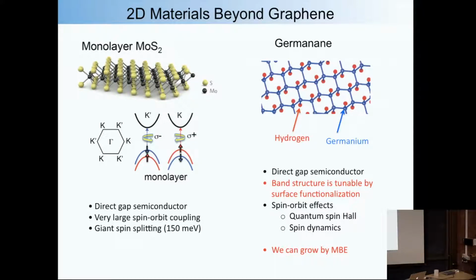The most work in the material is optics, like circularly resolved PL, also studying excitons. There's very strong exciton binding energies and so forth. Yeah. Is it possible to dope it with a gate into a valence band, or is it too big a gap? We have done it. We had to apply over 100 volts. And people have done it. Like people have made transistors where you go far into the p-type. You put on hafnium oxide thin and a top gate, and with just like negative 10 volts or something, it's p-type. So that can be done.